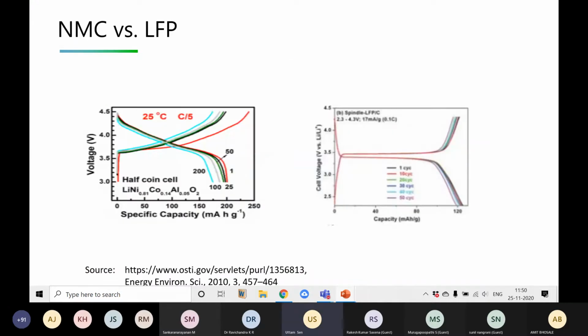So this is a representative graph of NMC and LFP. You can see this NMC potential is starting from 3.6. Okay, this is standard charge discharge potential plateau at C/5 rate. So you can see that it is gradually decreasing. So it is against lithium. So nominal voltage is around 3.9 volt.